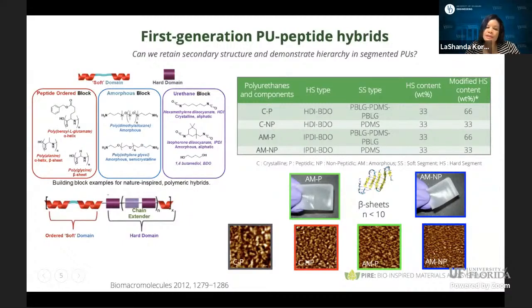We find these to be only beta sheet structures. So in this case, we use the block length with an N less than 10, which should give you primarily beta sheet structures. And the AFM images at the bottom actually demonstrate that we do have some phase segregation in our systems.